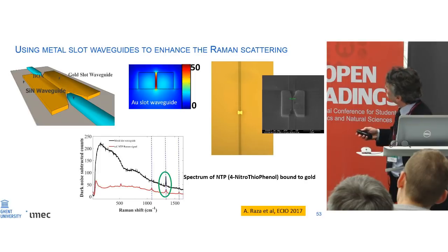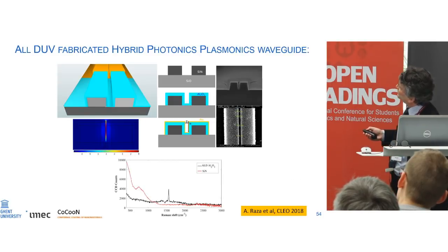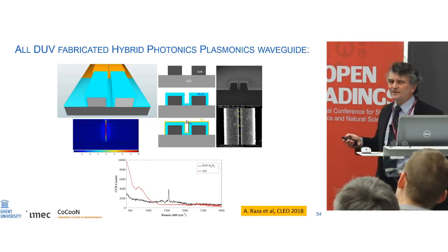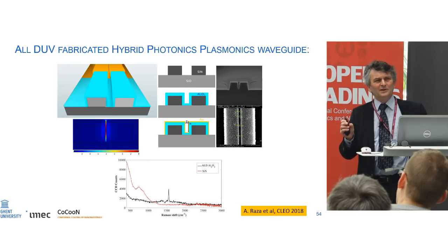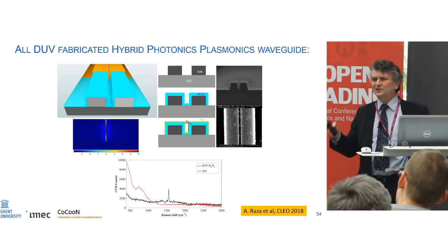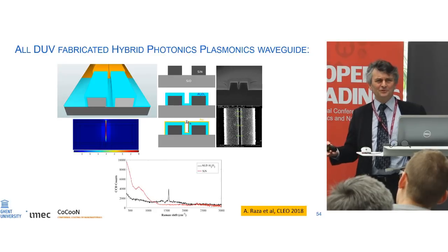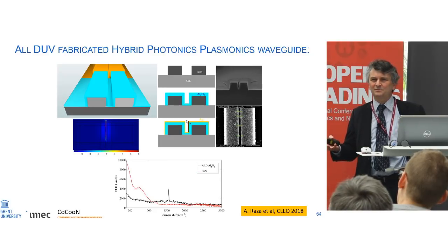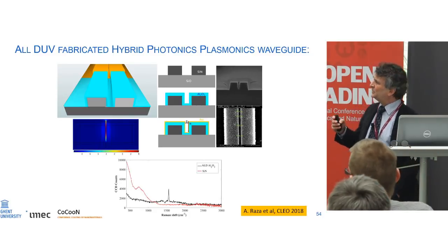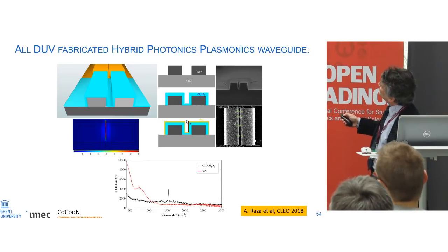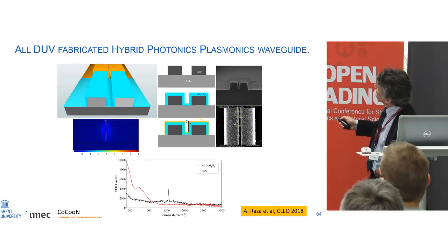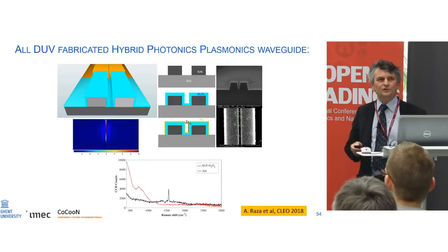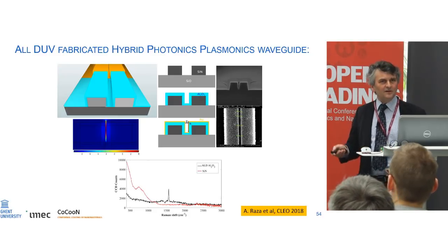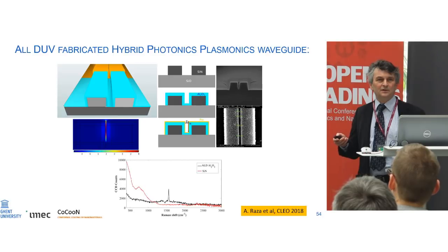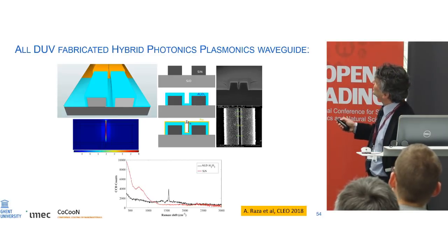This was a first example that we reported last year, but at CLEO this year we'll report a variation on the same theme, where basically making a metal slot of 20, 30 nanometers is not so easy, and you can do that with electron beam lithography, but you don't want to use electron beam lithography because it's not scalable to high volume manufacturing. What we did here is the following trick. We start from this slotted waveguide, and this still has a width for the slot of 100 to 150 nanometers. That's easily manufacturable in a CMOS fab. So this slot comes out of the CMOS fab.